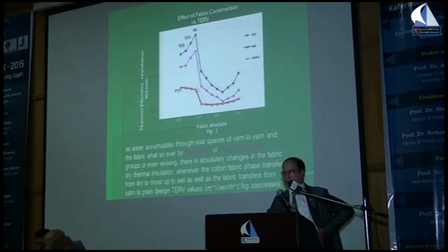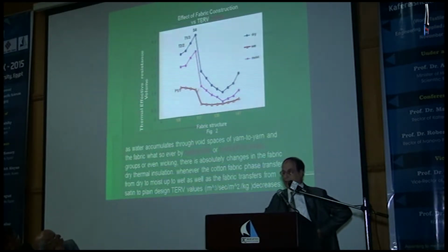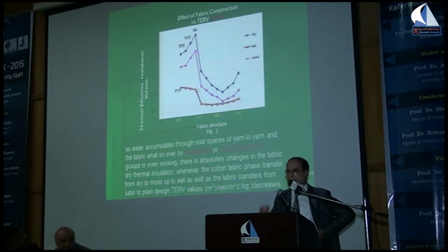We can see here the relationship between the fabric construction and the thermal effective resistance volume: the very wet fabric gives a very low thermal effective resistance because it is very wet, 100% water inside the fabric.